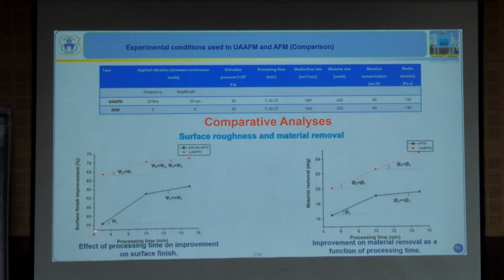At 5 minutes of processing time, we could reach 30% improvement in surface finish when we use simple AFM, and at 15 minutes we could reach only 55% improvement, whereas at 5 minutes itself we could reach nearly 65% improvement in UAFM. Means within 5 minutes we could achieve more than what we achieved in 15 minutes in the simple AFM process. It means that the process is rapid, and it is also increasing the finishing rate compared to simple AFM.